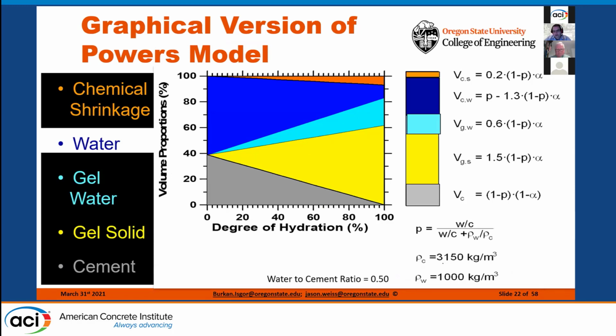And when Powers came up with his model, it was a 942-page treatise on the properties of concrete. And if you read that, you can decipher how to put all the equations together. But shortly after he came up with that, there was a group out of Scandinavia that said, you know, you could do this graphically, and it could help people to understand all of the intricacies of what you're talking about. And one of the really nice things that they did is they reformulated the equations that Powers had developed. And they essentially said that there's a linear relationship that takes place. And that linear relationship is based only on two things: the initial porosity, P, and the degree of hydration or the extent of reaction, alpha.